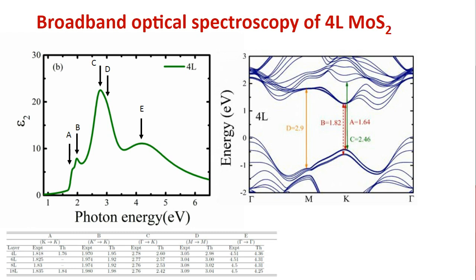So immediately we analyzed this E exciton, and we could assign this peak to direct transitions at around the gamma point, as shown here. So you can see that the energy difference matches very well. And as I was saying, direct transitions are very strong processes. So an E peak, you can see it's very strong, it's very broad. Again, I'm not showing here the band gap. This is the dielectric property. This is the imaginary part of the dielectric constant.